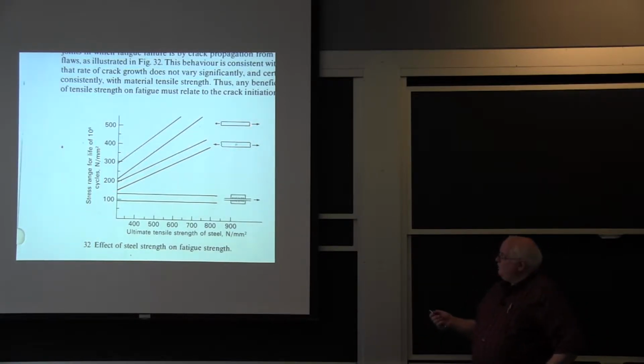The interesting thing, if I just have a straight bar of high strength steel and I plot the strength of the steel, there's a British book, so it's newtons per square millimeter, but 700 newtons per square millimeter, that's megapascals, is about 100 KSI yield strength steel. So this is HY 80 or HY 100, right about in here. And you'll see that the stress range for a life of 10 to the 6, a million cycles, increases with increasing strength on about a 45-degree slope.